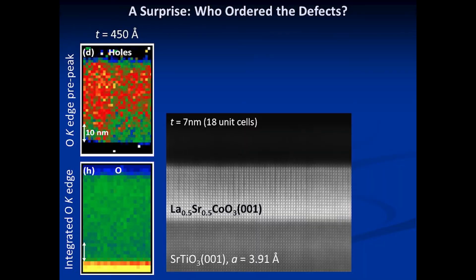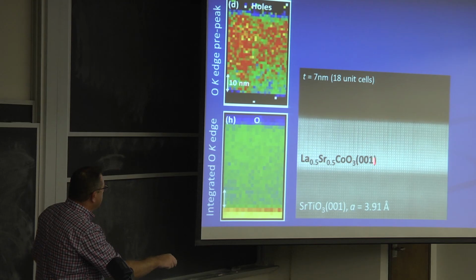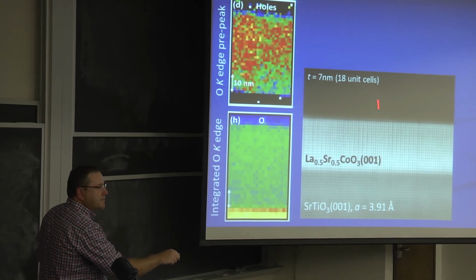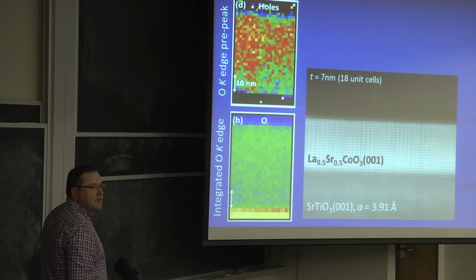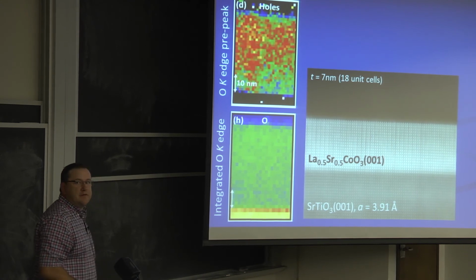Instead of working with these thick films, we decided, well, why don't we grow a very thin one, just the size of this dead layer. Here it's 7 nanometers thick. Let's image that and see if it still looks quite so perfect. And you can see with just the naked eye, it doesn't look quite so perfect. You see these dark stripes, right, that run perpendicular to the interface in this material. What are these dark stripes?